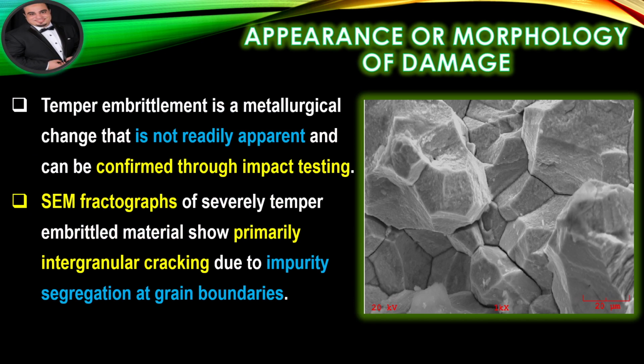Appearance or morphology of damage. Temper embrittlement is a metallurgical change that is not readily apparent and can be confirmed through impact testing. Please note that damage due to temper embrittlement may result in catastrophic brittle fracture. Scanning electron microscope fractographs of severely temper embrittled material show primarily intergranular cracking due to impurity segregation at grain boundaries as illustrated in figure.